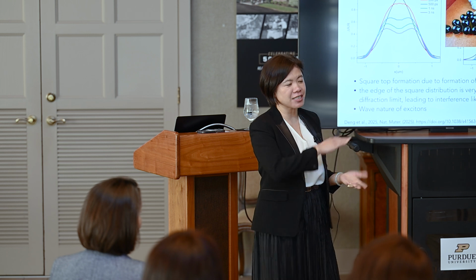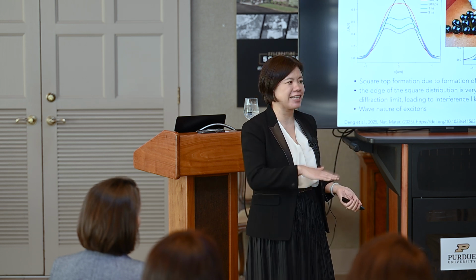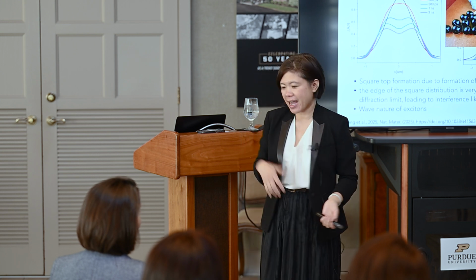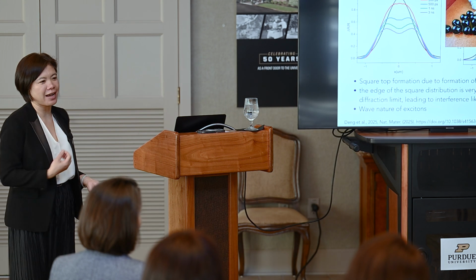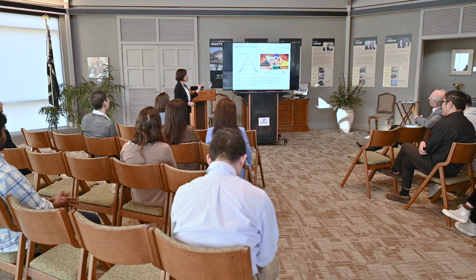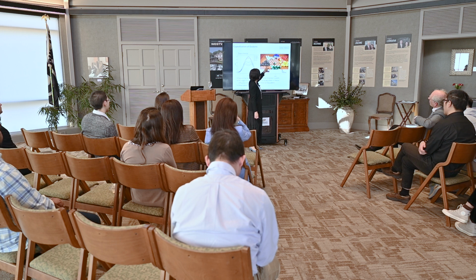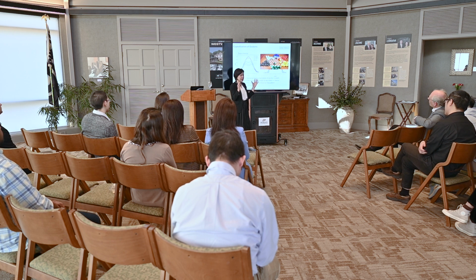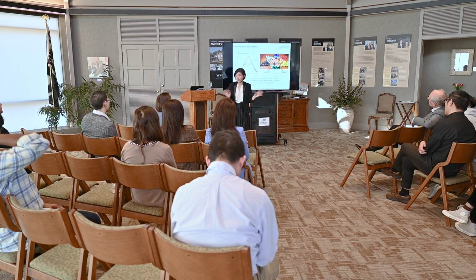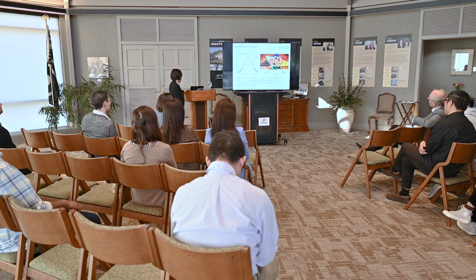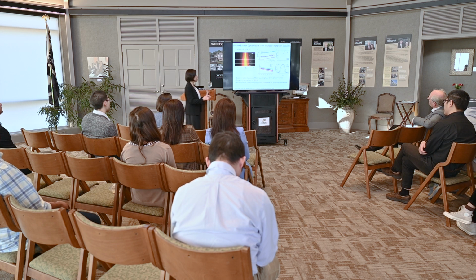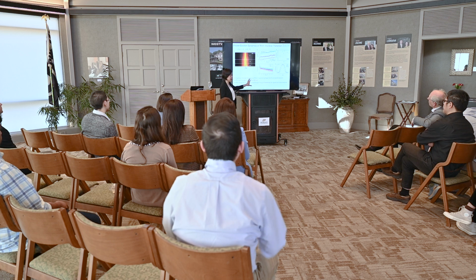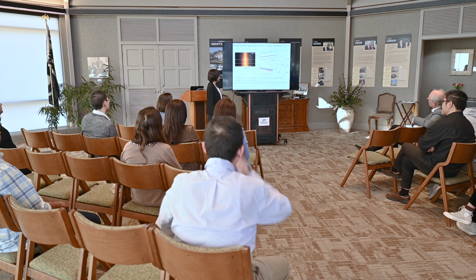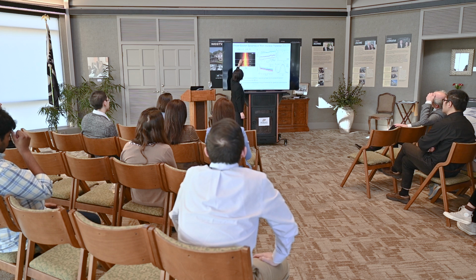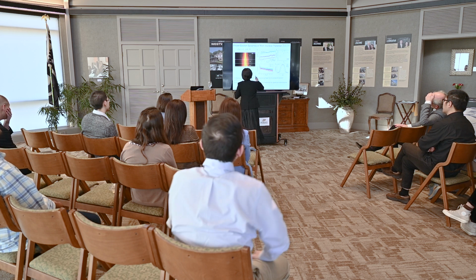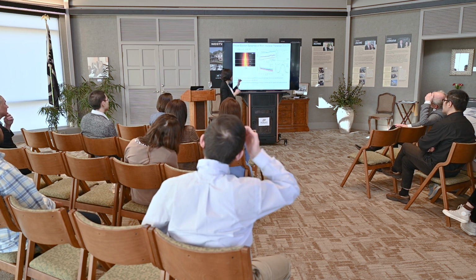Then if you look at the surface of the Chinese checkerboard, it will be flat, right? Because each hole has exactly one marble in it. And it's sort of like that, and I guess the quantum analog is that the interaction between the excitons leads to an insulating state, because the excitons repel each other, so they cannot really move, and they crystallize, and they form these packets like a Chinese checkerboard. And we can look at the long-time behavior when they form this Chinese checkerboard. What's very interesting is that this first line here, it basically gets down to up here, is when they start to form this square top.